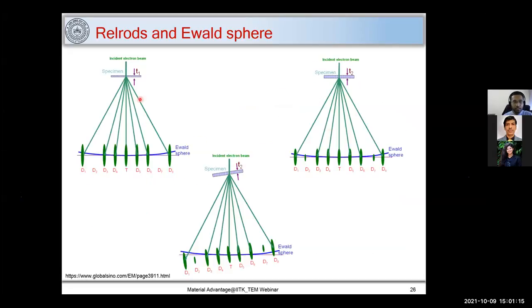So when I have a smaller thickness, I have rel rods in this direction, and their magnitude is represented here. When I increase the thickness, the magnitude of these rel rods decreases. So as I go on increasing, these rods will turn into kind of a sphere. So you can see that if I have a smaller thickness, the magnitude of rel rods is higher. If the thickness is higher, the rel rods are smaller.